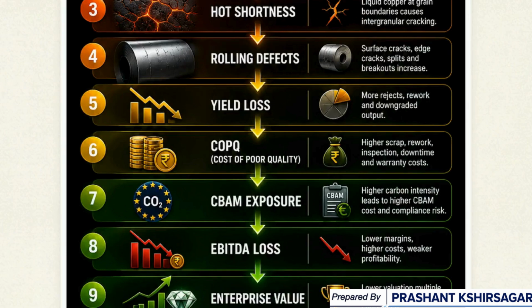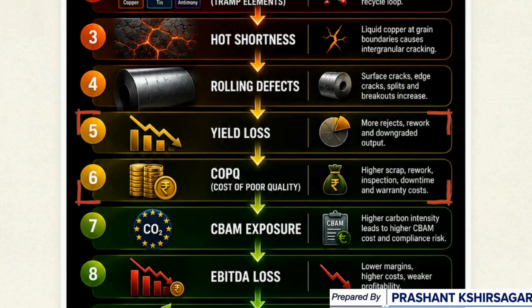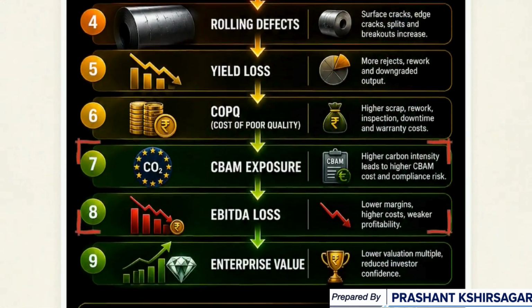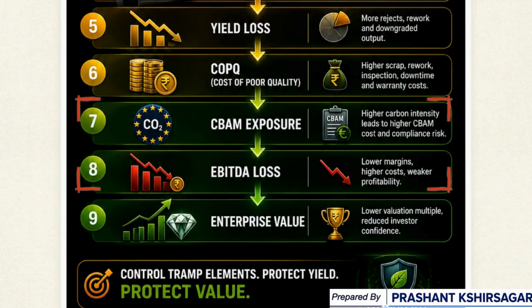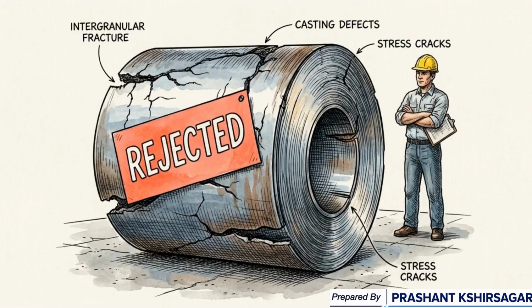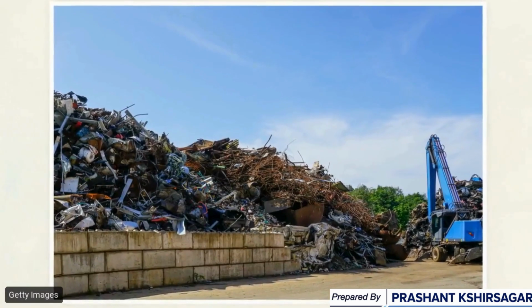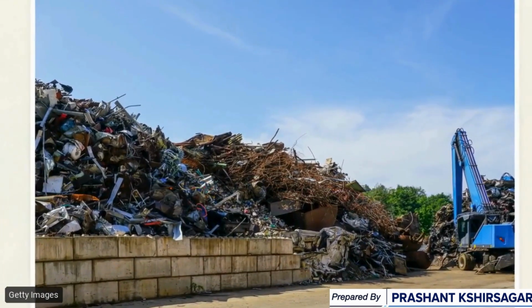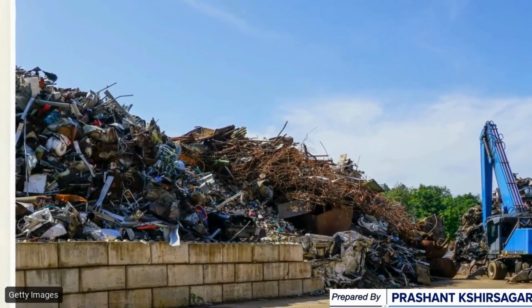This flowchart demonstrates how microscopic defects cascade into macroeconomic losses. Surface cracks cause immediate yield loss, which drives up the cost of poor quality. This directly inflates carbon intensity, increasing CBAM tariff exposure, and subtracts millions from EBITDA. Testing for these elements after the steel is cast is reactive and costly. To prevent hot shortness, Tramp elements must be identified and neutralized before the scrap crosses the melt shop doors.